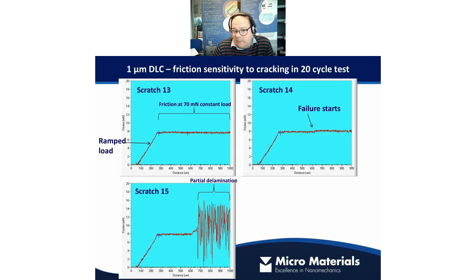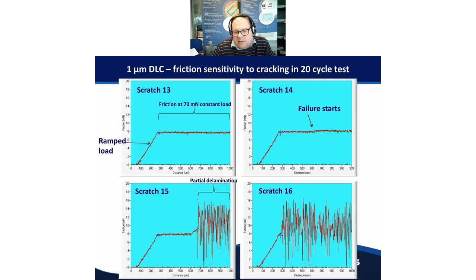Oh, well, it's developed. So now we've got a major failure commencing. We've got delamination, a partial delamination of the coating from the substrate, and by scratch 16 the whole track is destroyed. And so we can produce quite nice wear evolution charts in terms of mean depth of the probe versus scratch cycle number for multiple different samples, and compare how well they perform in a sliding scenario.